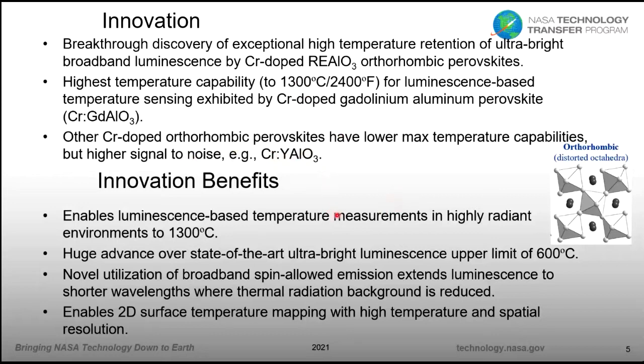The summary of the benefits of this technology: first of all, the high intensity of the emission enables luminescence-based temperature measurements when you have a background of high thermal radiation, because that strong emission will stand out against a strong radiative background. Typically, you only get very bright emission from the transition metal doped phosphors, compared to lower emission from the rare earths. And conventionally, the transition metal phosphor luminescence has an upper limit of about 600 C. So getting up to 1300 degrees C is a big step forward.